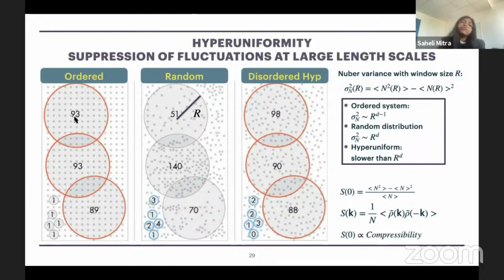To give an example, we can look into the ordered arrangement. In this case, there will be no difference in the bulk, and the only difference will be because of the surface where the surface is cutting the points. So in this particular case, the number variance will scale as r square instead of r cube. This is an example of an ordered hyperuniform system. Now, the most interesting part is when the system is disordered and yet it is hyperuniform. Hyperuniformity basically means that this number variance or the density variance is getting suppressed at large length scales.